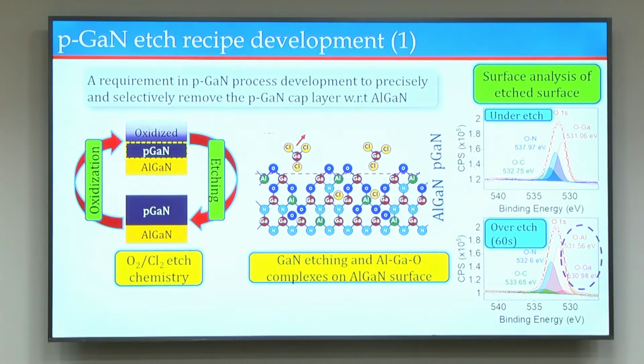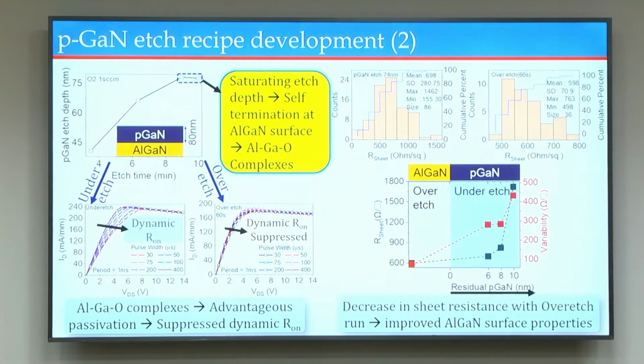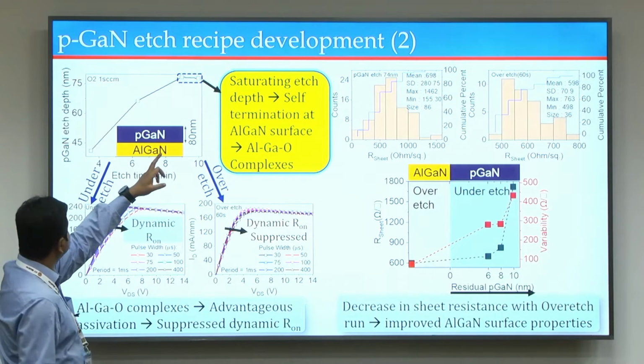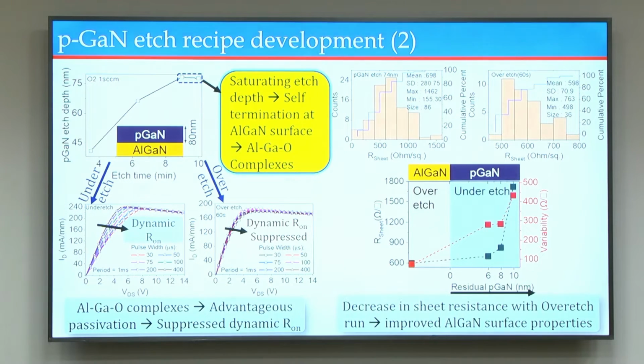Okay, so the other aspect I was talking about was the selective etch of the pGaN. So there are a lot of chemistries out there. You can use chlorine based chemistry, you can introduce oxygen and all, and what we found is that you have to basically use a chemistry which starts creating aluminum oxide the moment it sees AlGaN, and that can become a stopping layer for any further etch. So we developed an etch and a chemistry, and what we could get here is this kind of etch. So if you increase the etch time, at one point you don't see any further increase in the etch depth, and that basically is when no matter how long you continue the etch, the depth remains the same, which means now it has basically saturated the etch.